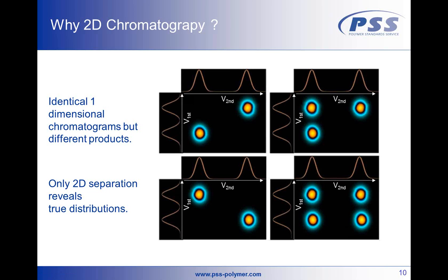So apparently, well, we have two species, and one of the peaks in the HPLC belongs to a certain peak in the GPC. But as you can see, in the lower part you have again two peaks, but the order is reversed. Here you have the high molar mass, or the first peak in the HPLC direction in the vertical is now the one which is on the right, and the peak which comes out late in the HPLC, the upper one, comes out in the SEC first.